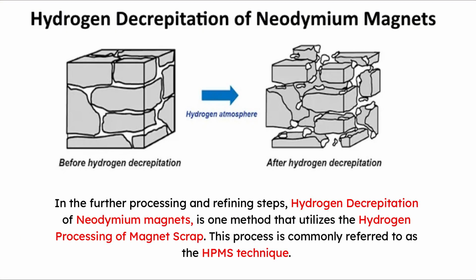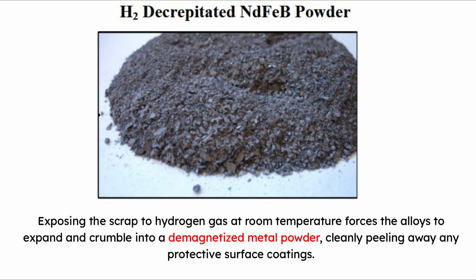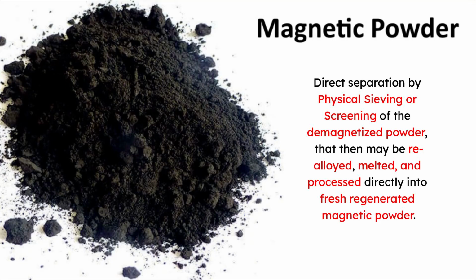In the further processing and refining steps, hydrogen decrepitation of neodymium magnets is one method that utilizes the hydrogen processing of magnet scrap. This process is commonly referred to as the HPMS technique. Exposing the scrap to hydrogen gas at room temperature forces the alloys to expand and crumble into a demagnetized metal powder, cleanly peeling away any protective surface coatings. Direct separation by physical sieving or screening of the demagnetized powder may then be realloyed, melted, and processed directly into fresh regenerated magnetic powder.